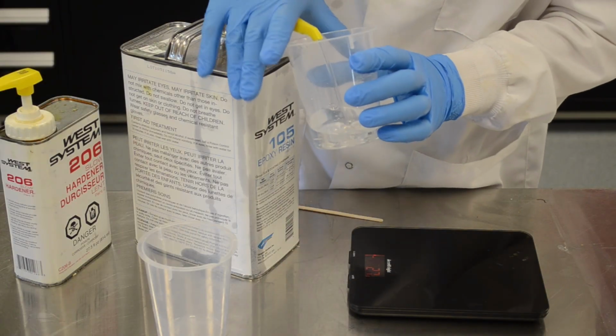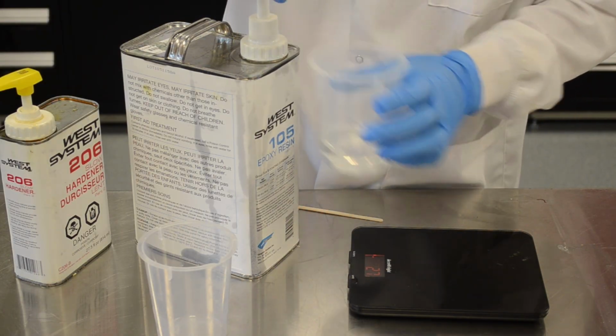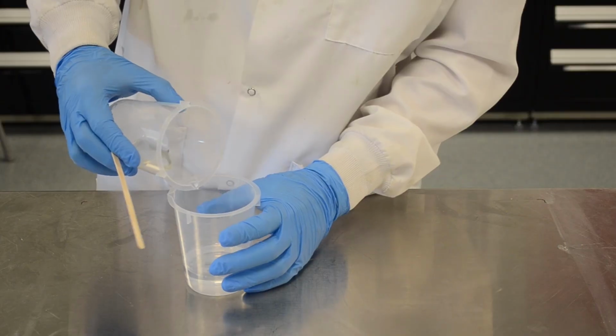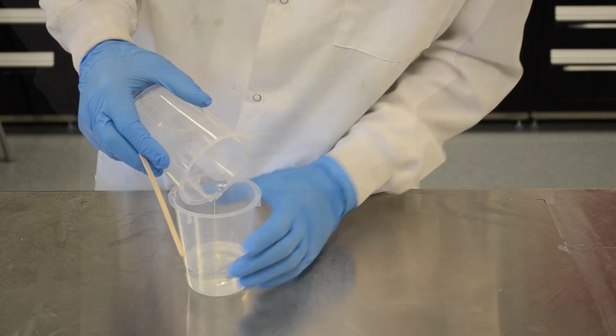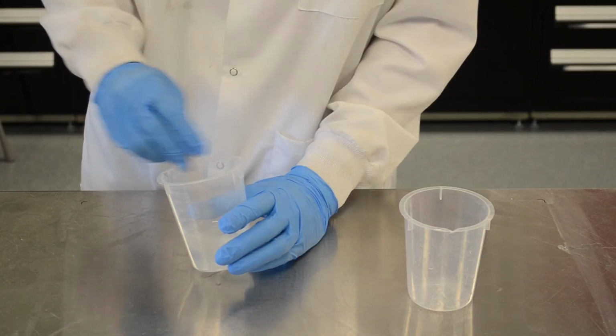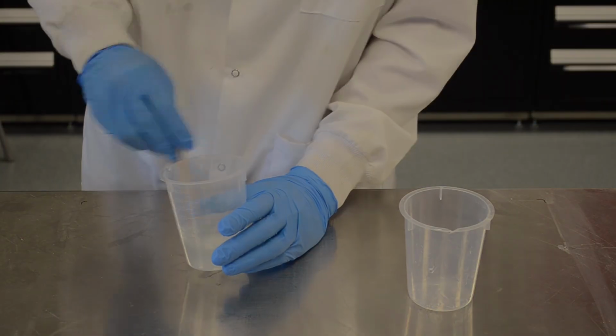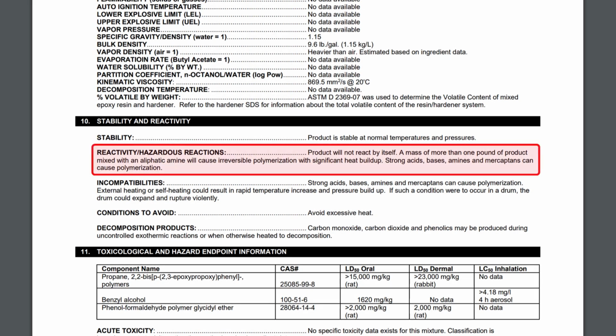We will be using 2-part epoxy resin, which will begin to cure after the resin and hardener are mixed. We will calculate an appropriate mass of resin based on our fiber mass and estimated final fiber volume fraction, plus a small amount to ensure we have enough. The cross-linking between resin and hardener molecules that occurs during curing is exothermic. As the temperature increases, this reaction occurs at a higher rate.